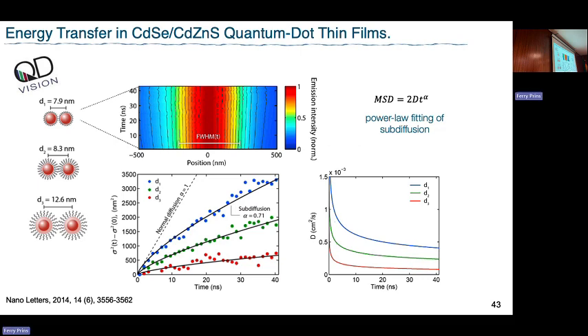So if you want to distinguish between excitons or free charges, you look at the power dependence of fluorescence. If the fluorescence that comes out of your signal is directly proportional to the laser excitation power, you know they're excitons, because it's a unimolecular recombination. Whereas if they're free charges, they need to find each other before they can emit, and then you're going to see something that resembles a quadratic dependence.